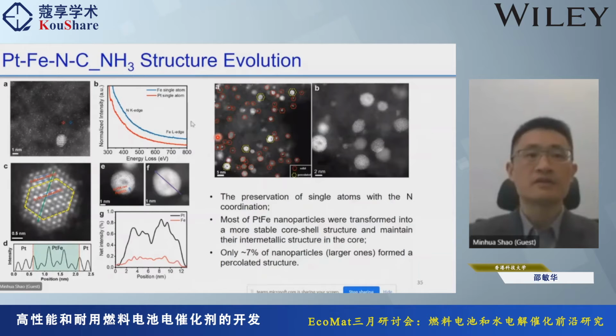Okay, so lastly, we show this kind of post analysis. After the 100,000 cycles, what kind of structure is left? You can see that for the nanoparticles, it becomes a core-shell structure. So you have a pretty pure platinum shell, and then you still have the platinum alloy. And for the larger particles, about 5 nanometers, you see this percolated structure. That means there is some porous structure. But the larger particles are very few. The majority are still small particles, and you still see these single atoms left, both platinum and iron. So that means this composition is still there.